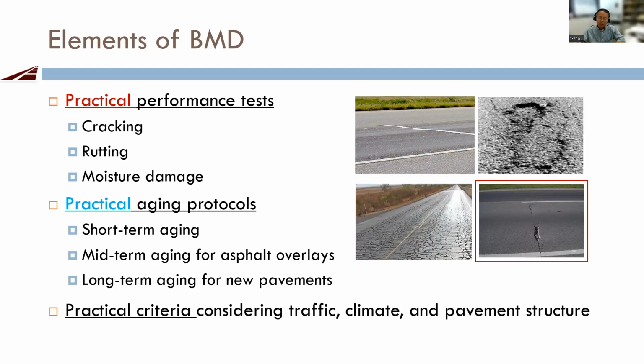For long-term aging, it is specifically for new pavement, because for new pavement design, we talk about 15, 18, 20 years, so you have to consider long-term aging. When we have the performance test and the aging protocol, then we can talk about the acceptance criteria. If you use the Hamburg test, we all know most people still use half-inch, and for different PG binders, for example, for PG 76-22, it is 20,000 passes, half-inch maximum rut depth. That considers climate, pavement structure, and traffic. All of this has influence on the criteria. So let's zoom in on each one by one.